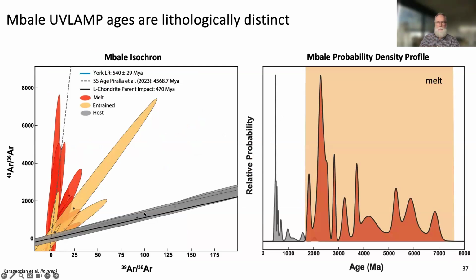This is our host. The gray band is our host, and the black line is 470. So our host is very close, slightly older than 470, just as the other data is for Mbale. This dashed line is the age of the solar system. And these are isochrons from the melt. Much of our melt seems to be older than the solar system, some of it less. And then some of those entrained clasts are in between.